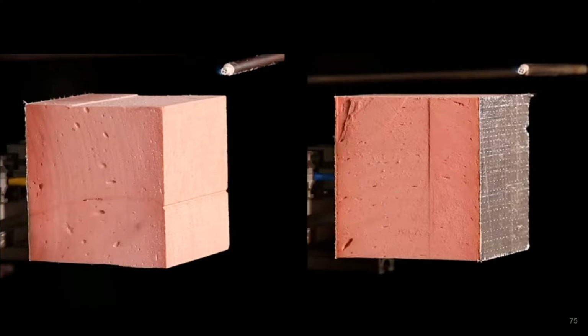After ignition, we'll see that there is no obvious melting or dripping from the sample, as was the case for the RS5000. And again, this is because phenolic foam, like PIR foam, is a charring thermoset polymer. We'll observe the formation of a char layer over the surface of the sample, which will again result in a reduction in the flow of flammable gases through the front face of the sample. This will again result in a reduction of the severity of burning, and eventually, in this case, extinguishment of the flame completely. However, we'll then observe that the char will begin to glow, and that the sample will gradually be consumed by a combination of smoldering combustion and physical loss of material from the foam's surface.